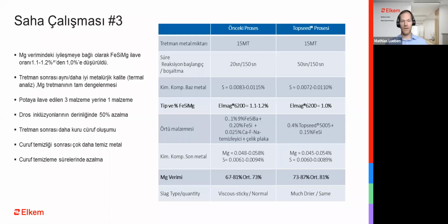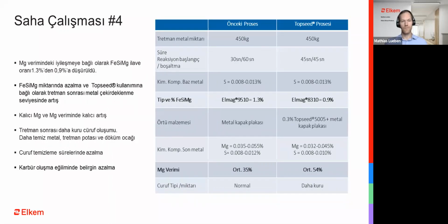And really important is that the customer was able to change from 3 products in ladle addition to 1. The ferrosilicon is still necessary because the customer is using base iron out of different furnaces. A reduction of 50% for dross inclusions has been achieved. And again, because of the Topseed, the slag is drier after treatment and the iron is much cleaner after deslagging. And also the result is for sure a reduced deslagging time. Next, please.